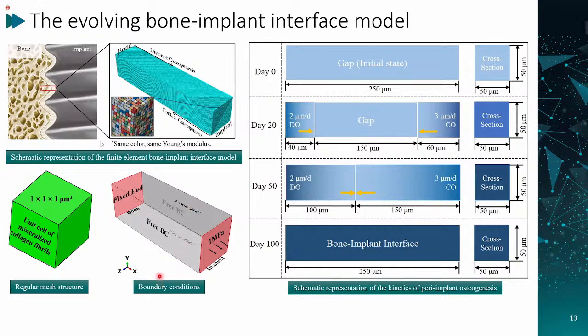And here shows the boundary conditions. Two sides: this side close to the bone is fixed, and this side near the implant we apply 1 megapascal tension force, and all the other sides are free boundary conditions. And this schematic shows the kinetics of the peri-implant osteogenesis cross-section, which means at day 0 is the initial most soft state between the bone and the implant, nothing here. But at day 20, they have the DO and CO fronts, the new bone grows to meet each other. At day 50, the DO and CO fronts meet here. After that, the whole interface becomes stiffer and stiffer until the final state.